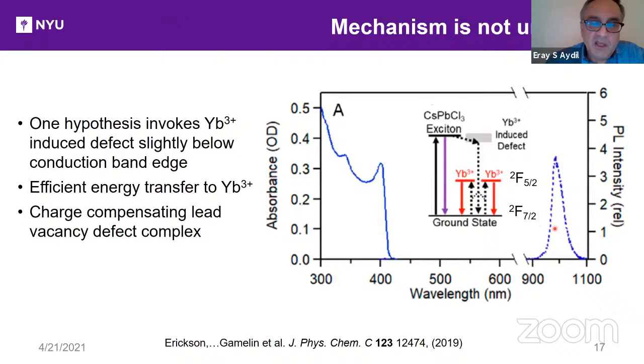So one might ask, well, what is the mechanism? How is this happening? And I can tell you that it's not understood, though there are hypotheses. And I'll tell you about one of them, probably the most credible one, by Gamelin's group. So one hypothesis invokes ytterbium 3+ induced defects slightly below the conduction band edge. And the idea is that the exciton is trapped by these ytterbium 3+ induced defects, whatever that might be. And then that exciton energy is split and transferred into two ytterbium ions. And the emission that you see here at 1000 nanometers, 1.25 electron volts, is the doublet F transition from an excited state to the ground state of ytterbium.